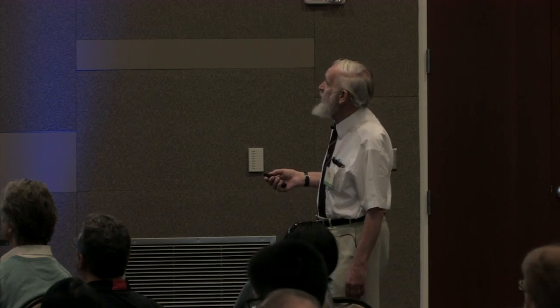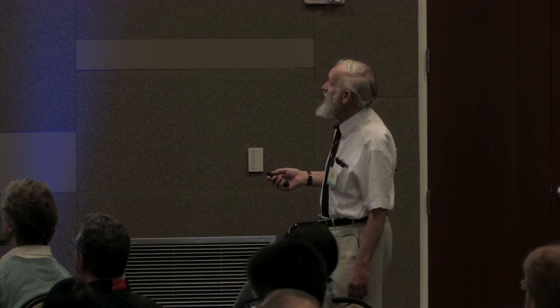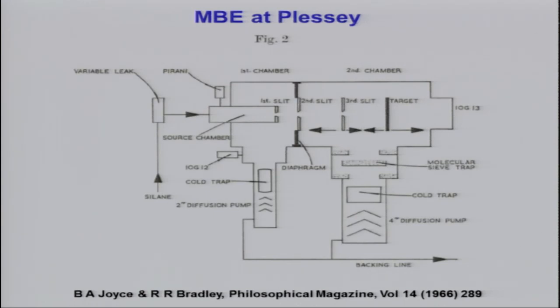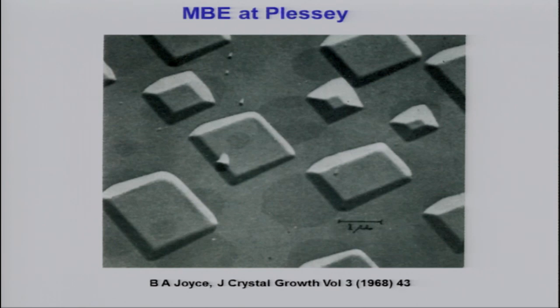The beam was formed and then impinged here on the heated target. So this was, from my point of view, a very early example of growth from a molecular beam to produce a semiconductor film. So here you can see silicon islands grown on the silicon substrate. They're clearly epitaxial, as you can see from this picture. So this is long before we were working at Mullard's.